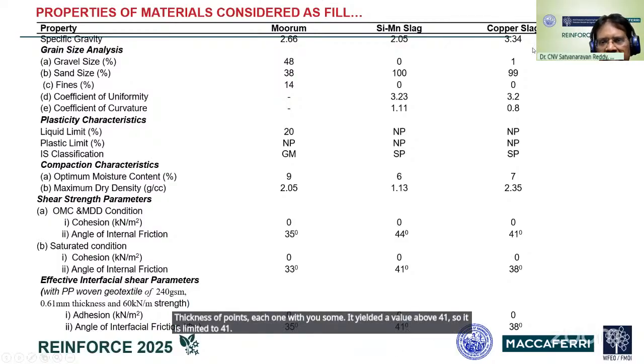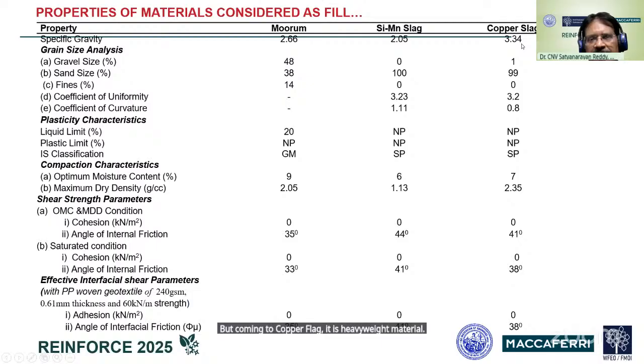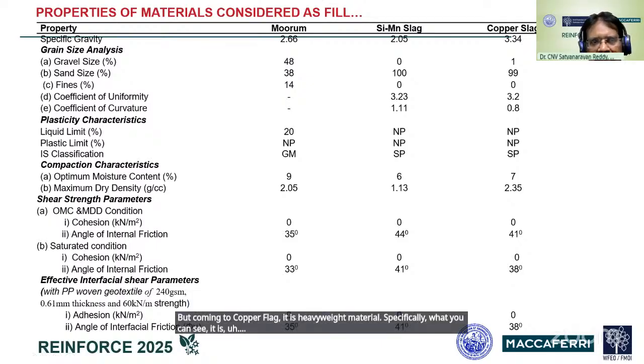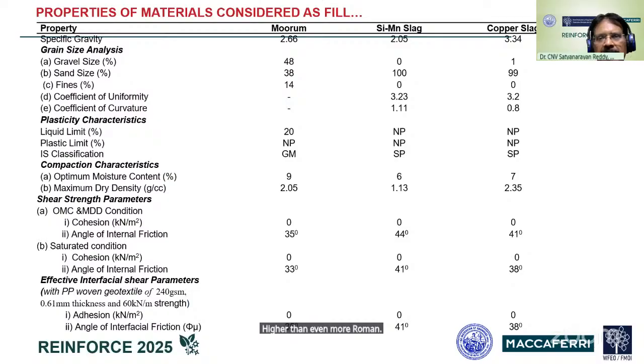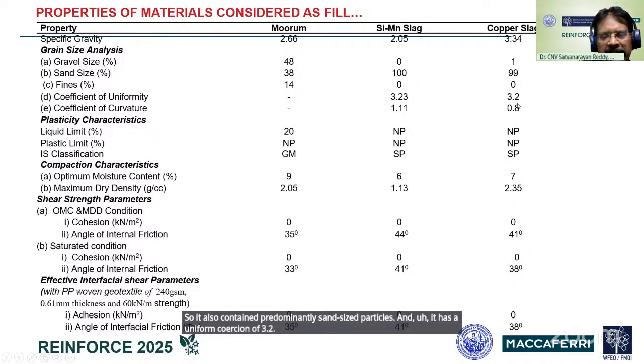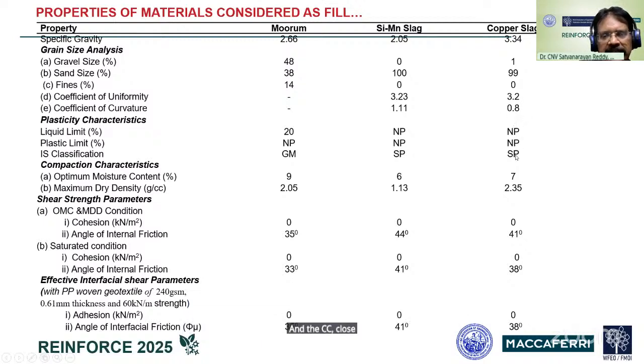Coming to copper slag, it is a heavyweight material. Specific gravity, you can see, is higher than even Moram, at 3.34. It also contained predominantly sand-sized particles, and it has a uniformity coefficient of 3.2 and CC close to 0.8, and the equivalent IS classification symbol is poorly graded sand, SP. Compacted maximum dry density was 2.35, and its angle of interfacial friction is 38 degrees.